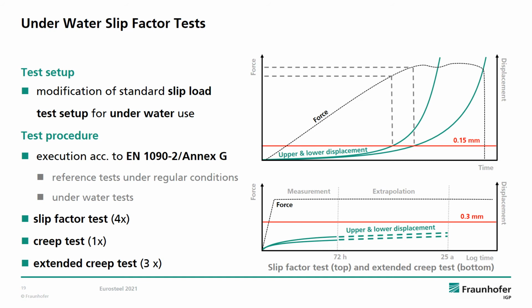To determine a so-called slip load, 4 slip factor tests have to be performed. The slip load determined gets then tested under static load within the creep tests. If displacement crosses the defined threshold in a certain amount of time, reduced loads have to be statically tested during extended creep tests until the acceptance criteria are met and the final slip factor and surface class can be defined.